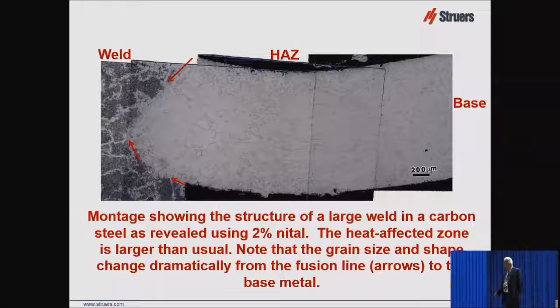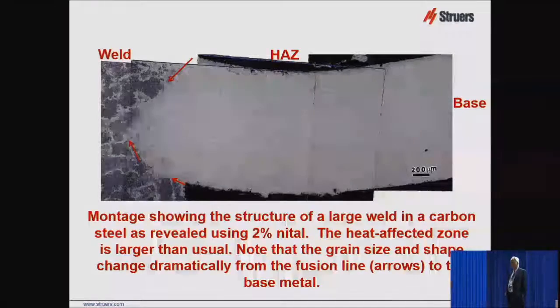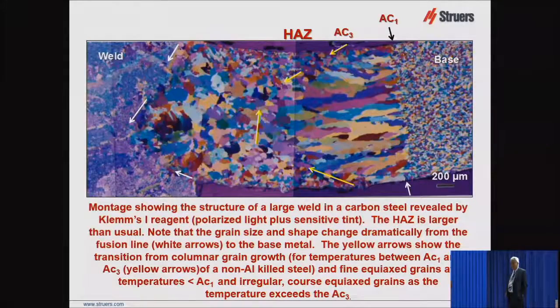And you can see the heat affected zone is starting roughly here, where it's above the Ac3. The Ac1 is going to be over here for the steel, and the Ac3 here, and then this is the fusion line over here. And you can see the grains look sort of coarser as you go back towards the left. But look at it now in color. Is that not remarkably better? Isn't that much easier to understand what's going on than the Nital?